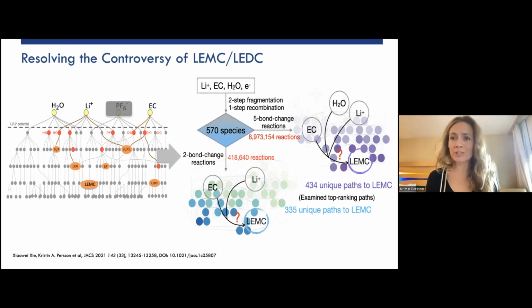Water is a nasty species when it comes to reaction networks, because it has these radicals that really like to react with everything. So we constructed two networks, one with water and a maximum of 5 bond change reactions, and one without water. The one with water went up to 9 million reactions, and the one without about 500,000. We looked at all the different paths that would form LEMC, contrasting that to the known paths of LEDC. And what could we learn from that?